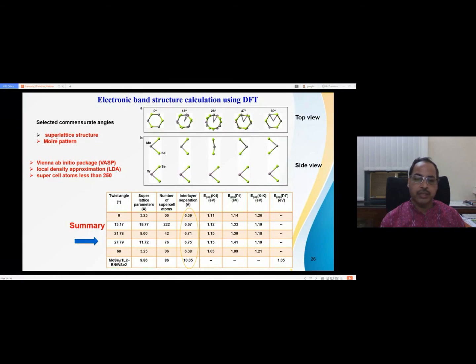Okay, and when we do this on hexagonal boron nitride layer, the layer separation increases, and I have not shown it here, but we cannot get anything. We cannot get any interlayer exciton. We cannot get any coupling or quenching. We cannot get any peak shift also.